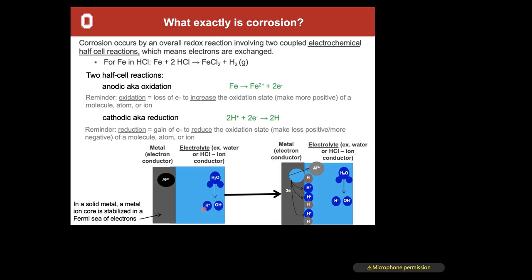So the H+ in my water reacts with that aluminum, and this paired reaction will occur, although here it will be aluminum now, right? The aluminum 3+ ion will float out into the water, be on its own, and the 3 electrons are going to come to H+ atoms that are adsorbed on the surface and make adsorbed hydrogen. So you get hydrogen generated. Note, depending on the cathodic reaction, you can also make OH-. There are different reactions that can occur. For iron and hydrochloric acid, it is this one here, right?